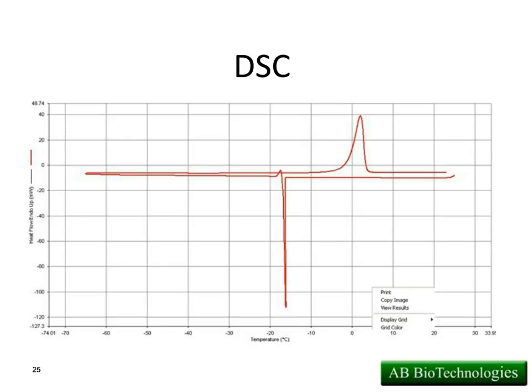Again, with freezing, we see freezing point depression, we see supercooling. So it essentially becomes meaningless information in regards to thermal characterization. The only reason we look at this is to see where the sample is finally freezing. You know, negative 20, negative 18, very typical. What we're looking for is if samples don't freeze until negative 45 or lower, then you've got a real problem. You can't even get the sample frozen. If you can't freeze a sample, you can't freeze dry the sample, is what I'm getting at. So we essentially throw away the cooling curve and then look at the warming curve for our thermal events.